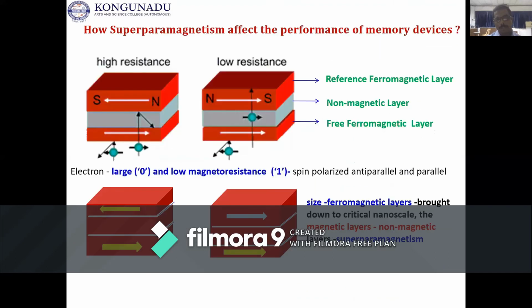So, what is the problem with the superparamagnetism? How is it affecting memory devices? As far as memory devices are concerned, they have two ferromagnetic layers separated by a non-magnetic layer in between. So, it is a three-layer device. When the spins of the magnetic layers are anti-parallel, the magnetic memory device will feel a high resistance, where you can store a bit zero. You know that a computer stores bits 0 and 1. So when it's high resistance, due to anti-parallel spin, you can store a bit zero. When you have a parallel spin between the two magnetic layers, you can store a bit 1.